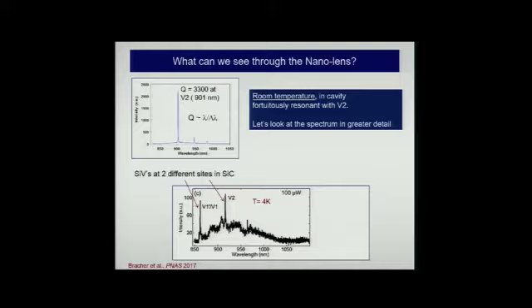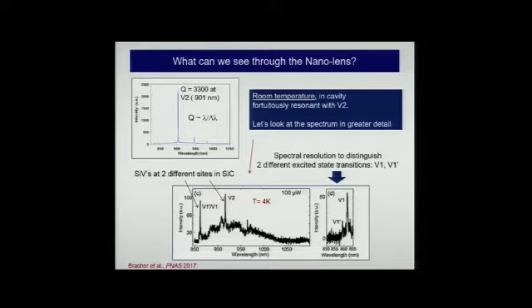But in an untuned cavity, if we take a closer look, so this is at low temperature, this is not even fortuitously tuned. So what we're seeing is broad background. We're seeing V1 and V2. These are the two silicon vacancies. But when we have enough spectral resolution, we notice that V1 has some interesting additional features. And so this is part of our journey in looking through this unusual lens. If we look a little bit more closely, we notice that around V1, and I've already labeled it V1 prime, I can distinguish two transitions. So there are two transitions associated with this one particular silicon vacancy.